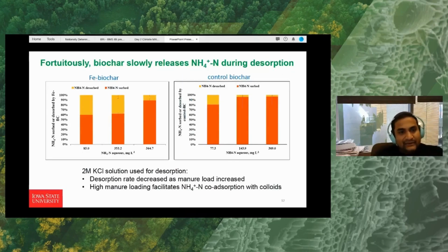So again, for the ammonium desorption, we did the iron biochar and control biochar. And biochar shows slow release of the ammonium nitrogen during the desorption study. We used the 2 normal KCl solution for the desorption study. And the desorption rate decreased as the manure load increased, and also the high manure loading facilitates the ammonium adsorption, specifically in the colloidal portion. So that means with high manure, the desorption rate decreased because the ammonium goes into the colloid part. Iron biochar desorbs a little bit higher ammonium compared to the control biochar.